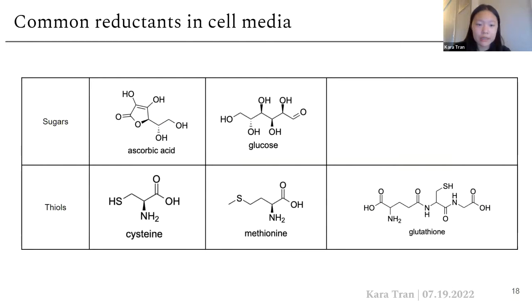So with this in mind, we designed an experiment to test if there was interference in our assay from reductants in the media. Here is a table of reductants found common across many media types, which we screened. We chose cysteine and methionine as model amino acids that could be easily oxidized, which contain a thiol and a sulfide functional group respectively, as well as glutathione, a tripeptide containing a free thiol. We also screened ascorbic acid because it is commonly used as an antioxidant, and glucose, which is a model reducing sugar. We screened glycine as a control to verify that the amine or carboxylic acid of general amino acids are not the specific groups that are reacting with MTT.